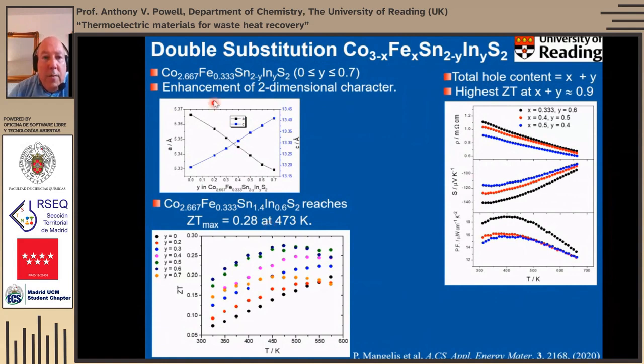Now, we've done quite a lot of combinations of cobalt, iron, tin, indium, but what we find is that the highest ZTs are always at a similar total hole content. So that is when the iron content, which is given by x, and the indium content given by y, add up to 0.9 or thereabouts.